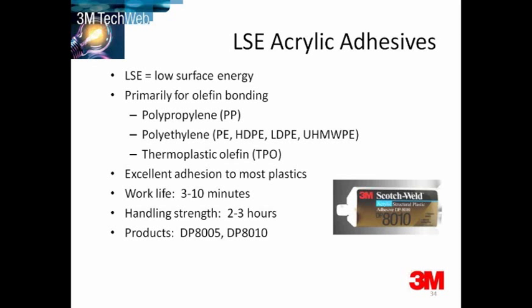We have two very special products: DP8010 and DP8005. These are known as low surface energy bonders — a special type of acrylic formulation which will bond to low surface energy plastics such as polypropylene, polyolefins, and PE in general. Work life is 3 to 10 minutes. Strength can be achieved as quickly as 45 minutes, depending on the substrates, environment, and temperature. These are excellent products for bonding plastics.